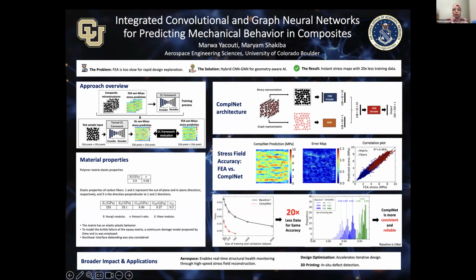CompiNet looks at the problem through two complementary lenses. The graph neural network captures the big picture, understanding the overall material behavior by considering the position and interaction of fibers. At the same time, the convolutional neural network focuses on the fine details, tracking how stress moves at the pixel level. Given a composite microstructure and loading condition, CompiNet predicts the full stress distribution across the material.